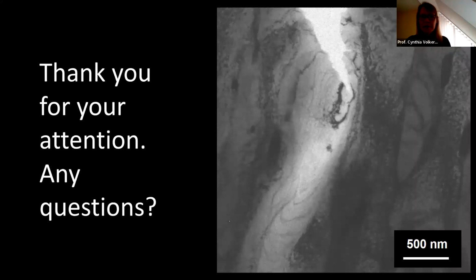And that's why we conclude that the electron beam and the conditions in the microscope are significantly enhancing the fugacity of the hydrogen. We are not the only ones to see that. There are many studies on different materials, in different countries, in different microscopes, that show that very low pressures of hydrogen, below what would be expected outside of the TEM to produce an effect, can produce a large effect in the TEM. So that the fugacity is raised, I think, is clear from the observations. How it's raised remains a mystery.